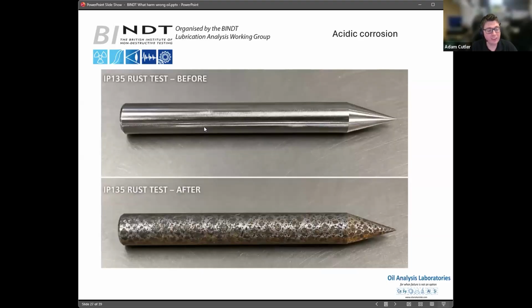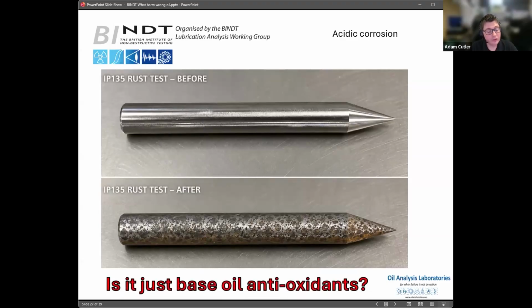So we can see here, we have a test specimen, and normally we do this test over 4 or 24 hours, depending on the client's requirements. This is after 40 minutes of testing, and this is not the anti-rust corrosion additive being spent. This is actually the oil has been split because we mix oil and water together to see how well it prevents corrosion. But the water had split the oil, so it split the ester into acids, and this was causing corrosion. So is it just the base oil and antioxidants that's causing issues?